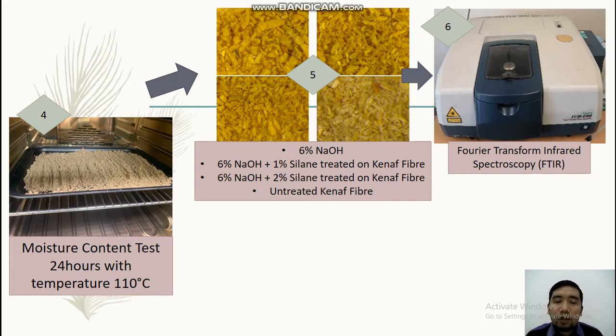at a temperature of 110 Celsius. Okay, after that, when the fiber is done, for the chemical testing we use FTIR for 4 types of fiber: the fiber with 6% NaOH, the second one 6% NaOH with 1% silane treated Kenaf fiber, the third one 6% NaOH and 2% silane treated Kenaf fiber, and the last one is untreated Kenaf fiber.